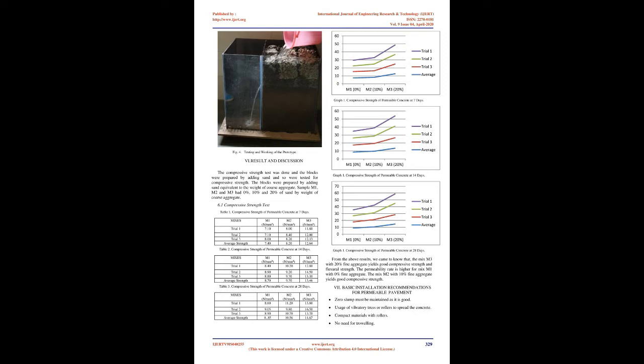4.3 Specimens. Cubes of size 150 mm were cast and tested for compressive strength at the age of 7, 14, and 28 days, and beams of size 150 x 150 x 700 mm at 28 days for flexural strength as per IS 516. All the specimens were kept immersed in water until the time of testing.